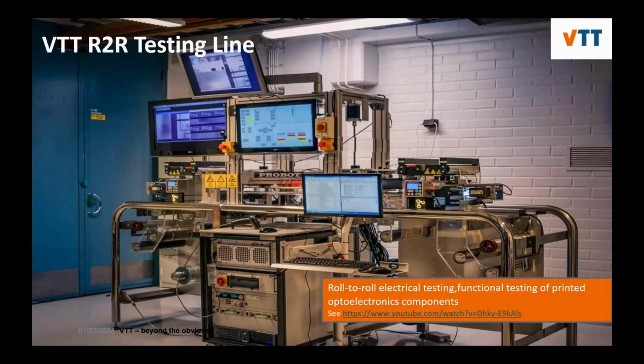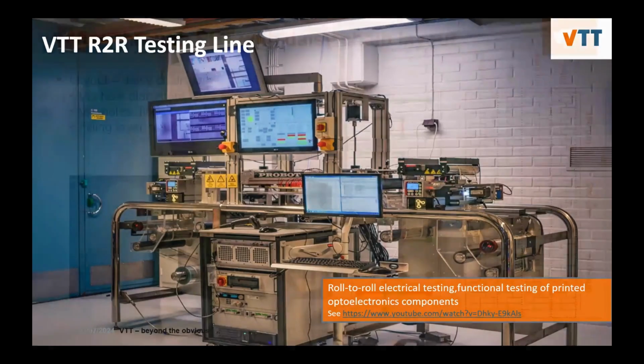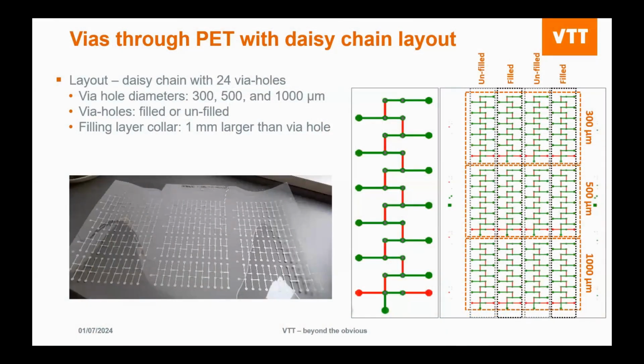This is a stop-and-go process where we have a flatbed of pins to measure the resistance of the particular metal that we've printed. In this particular use case, we did a daisy chain structure. You can see this is 1 repeat length on our printing line. Our repeat length is about 40 centimeters by 30 centimeters.